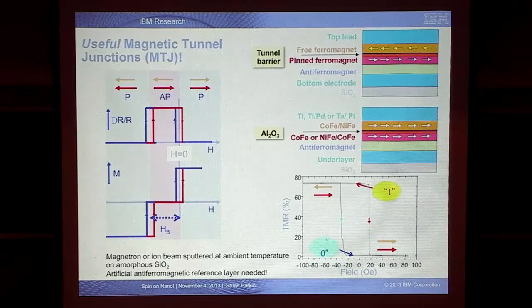Now, to answer your question briefly, I mentioned we have to control the magnetic moment directions in these sandwiches using what I'm going to call spin engineering concepts. This is a diagram of how the magnetic moment responds to a magnetic field. Usually, for magnetic materials, this response curve, or hysteresis curve, will be symmetrical about zero magnetic field. But we can change this by coupling this magnetic material to what is called an antiferromagnet. It's a material in which locally the magnetic moments of atoms want to be antiparallel to each other from one atomic site to the next. So in essence, there's no net magnetization, except at an interface, where this is broken, and it turns out there is a small net imbalance in the moments of this antiferromagnetic material, leading to a very, very strong internal magnetic field that can be enormous.